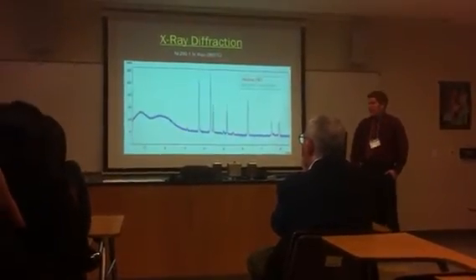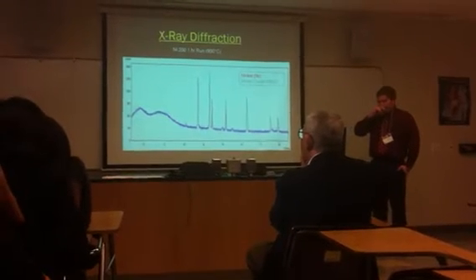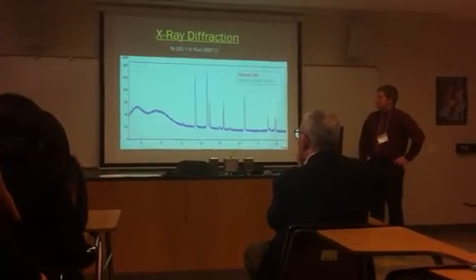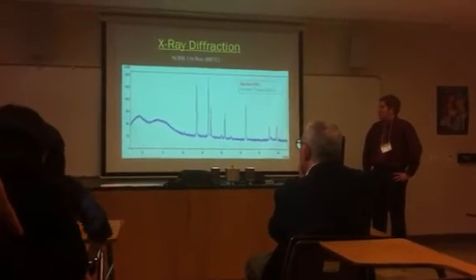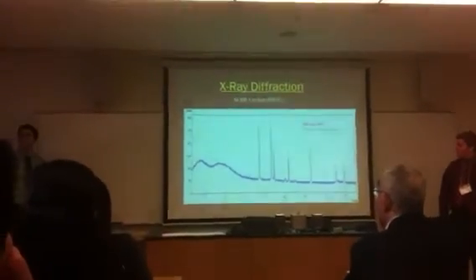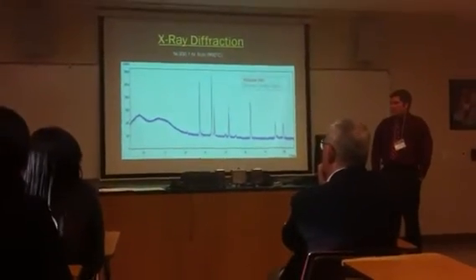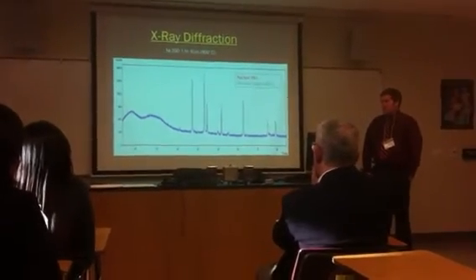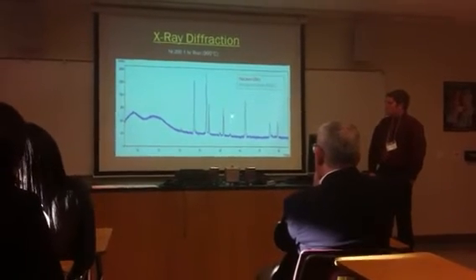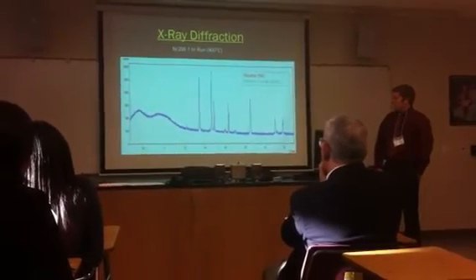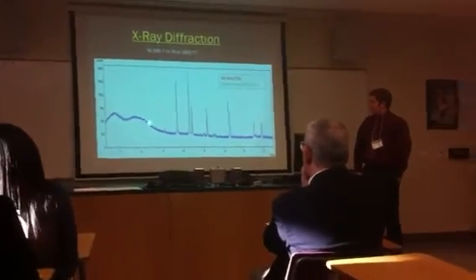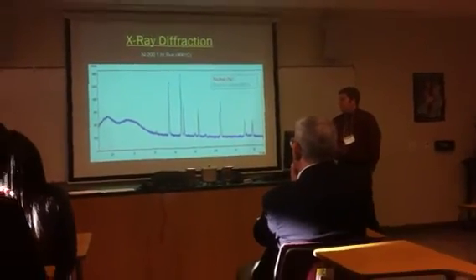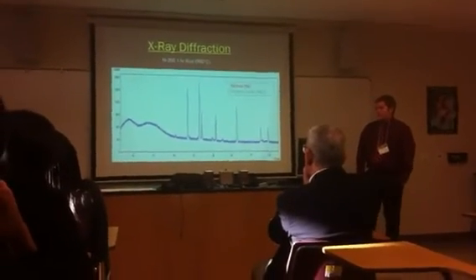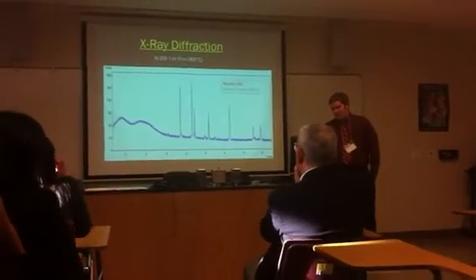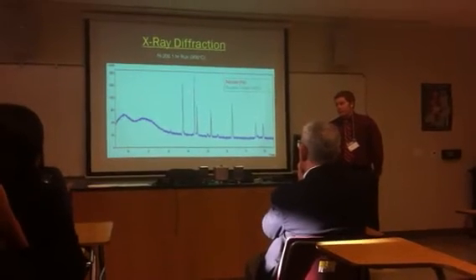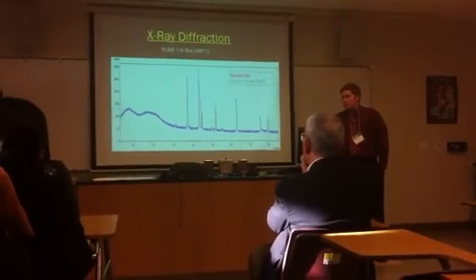So to determine what was actually on our sample, what kind of oxidation was formed, we use X-ray diffraction. Here's a nickel 200 sample after a 1-hour run at 900 degrees C. On the y-axis, we have our intensity in counts, and on the x-axis, we have our diffraction angle. As you can see in the red, the peaks characterize nickel, which is our substrate. And then these peaks in green, I believe, are our nickel oxide, which is still there after all the washing. And it's important to note that these were done on the surface. These are surface X-ray diffractions of our samples.